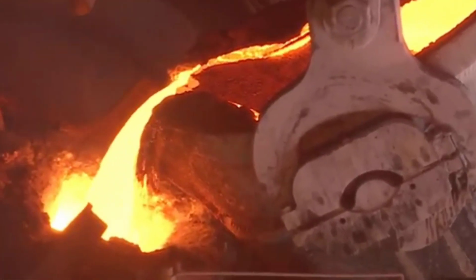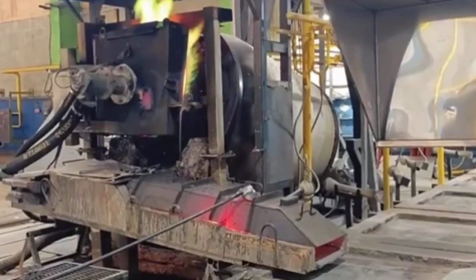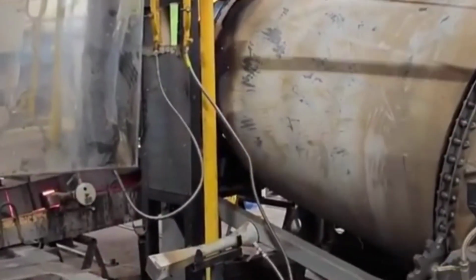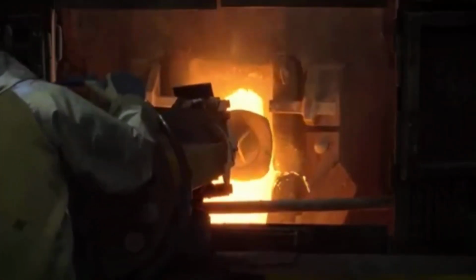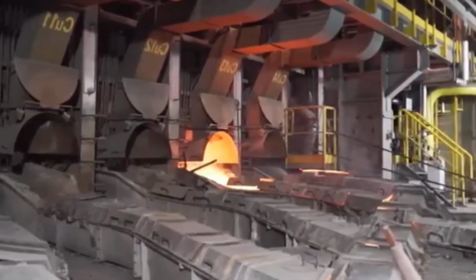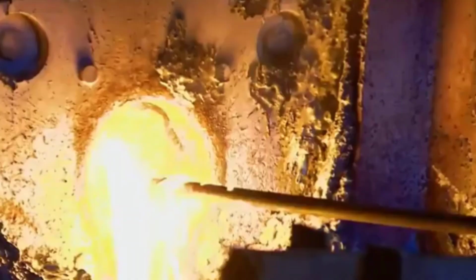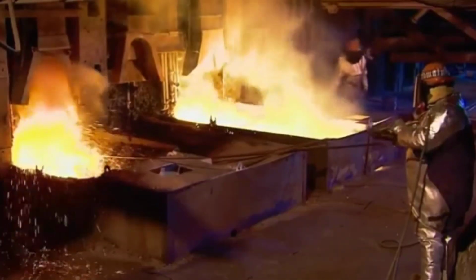The copper concentrate from flotation, usually containing about 30 to 40% copper, is fed into smelters, massive industrial furnaces that can stretch dozens of meters and reach temperatures up to 1,200 degrees Celsius, hotter than volcanic lava. Inside, the material is heated together with silica and other additives, which help remove impurities.